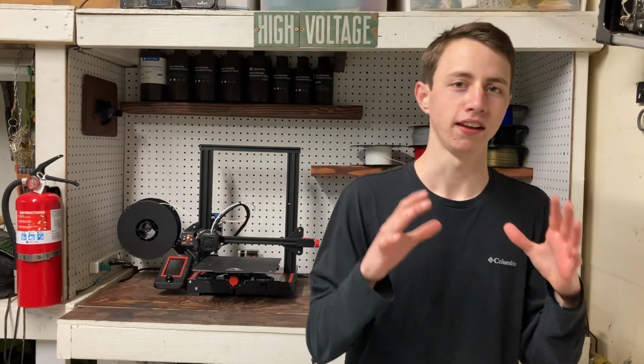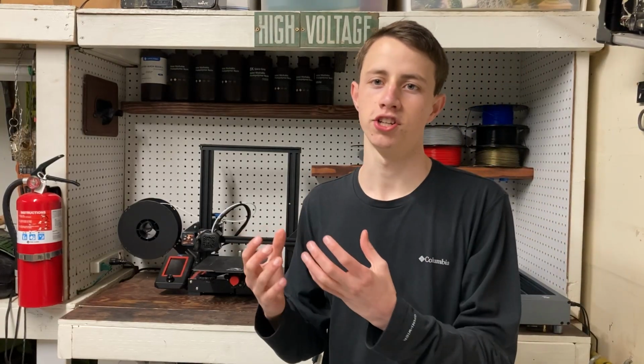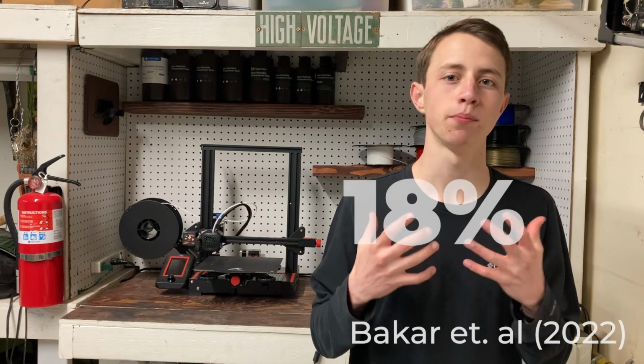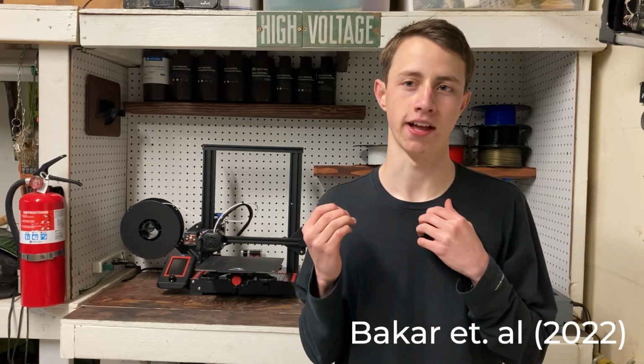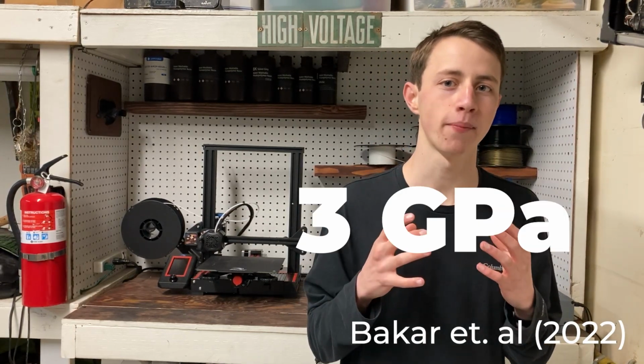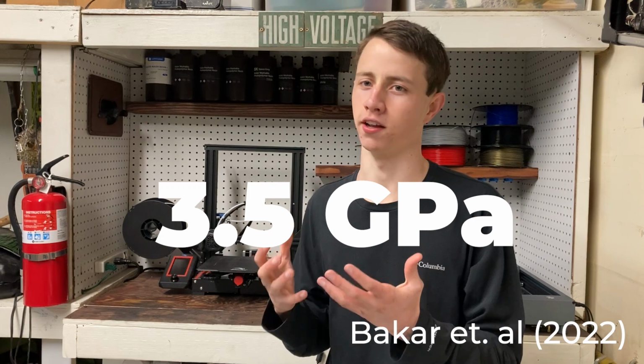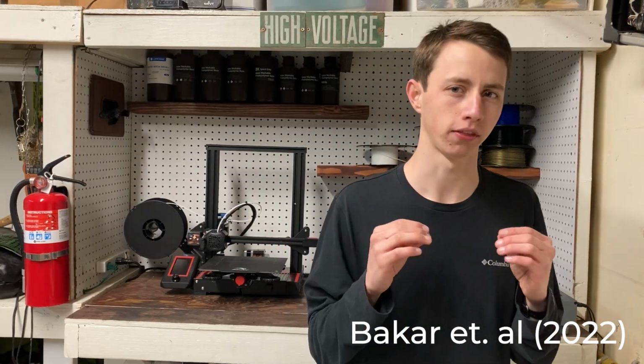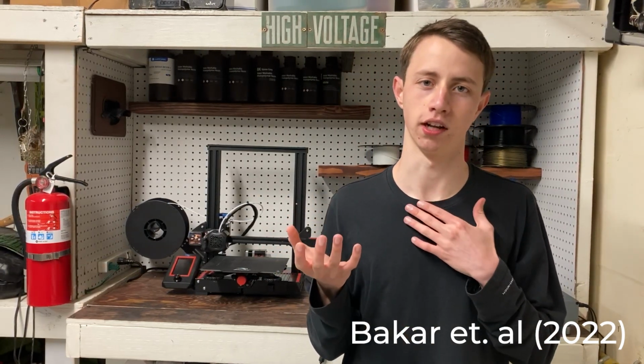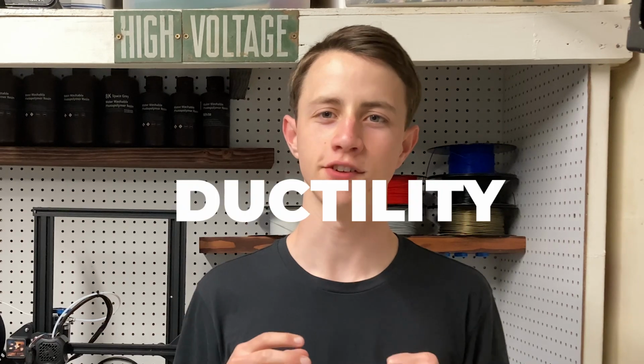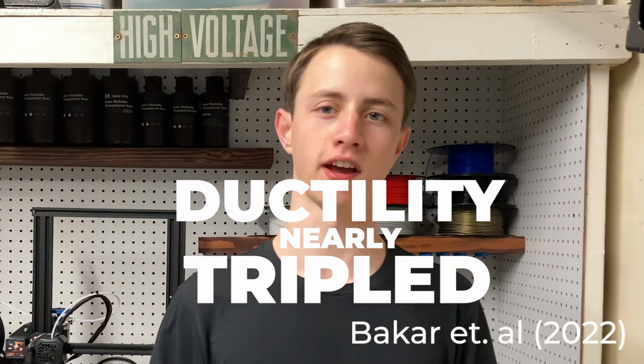A reasonable approximation, I'm sure. Anyways, here's what they found. The samples of PLA left in the natural conditions and in the oven saw an 18% increase in their modulus of elasticity, rising from 3 gigapascals to about 3.5 gigapascals over the course of a month due to an increase in crystallinity. Additionally, the ductility of the samples nearly tripled as time passed.